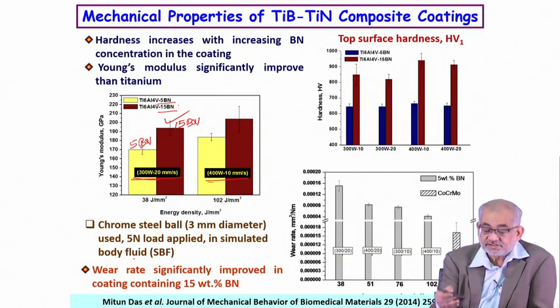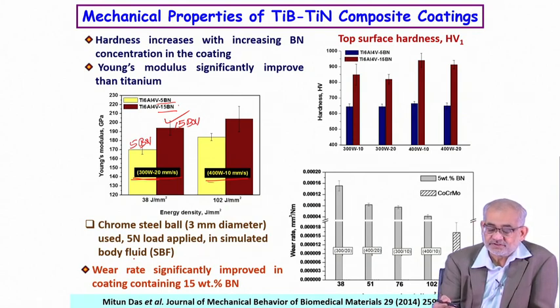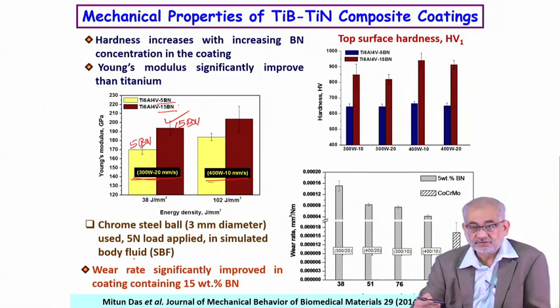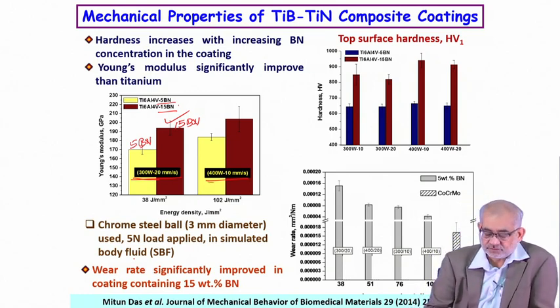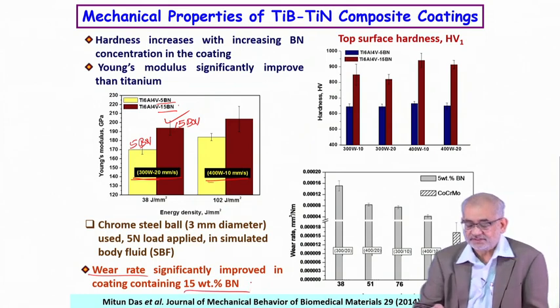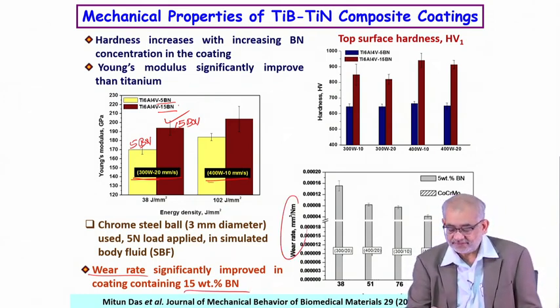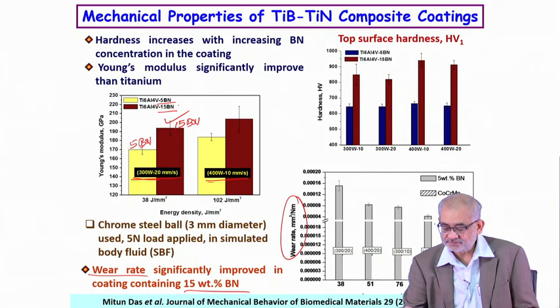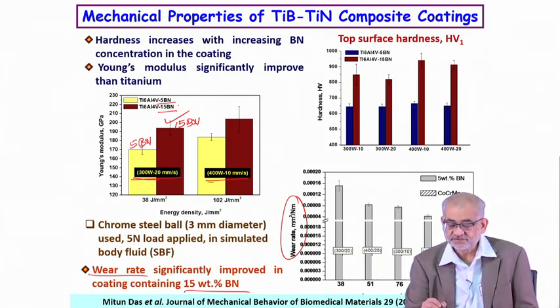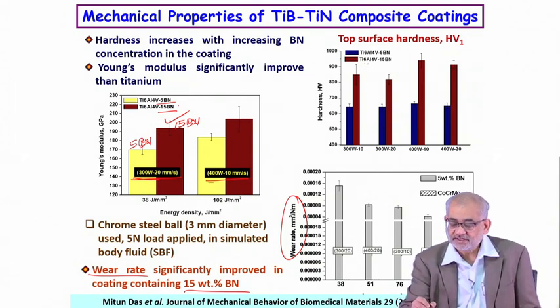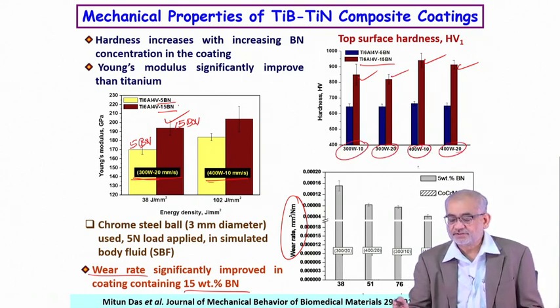So this kind of coating would be very useful not only on titanium-based components but also on steel to develop wear resistant coatings. In fact, wear resistance does improve significantly when you apply such coating. So the wear rate, what we realize, is very significantly decreased because of this coating, and most importantly, the hardness is exceedingly high. These are for different combinations of laser power and speed.